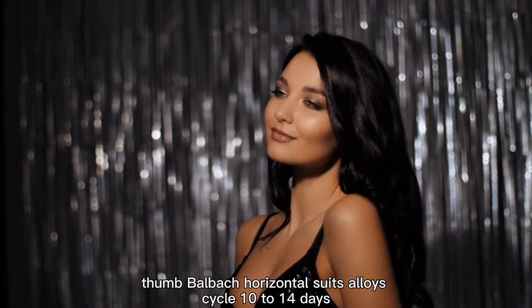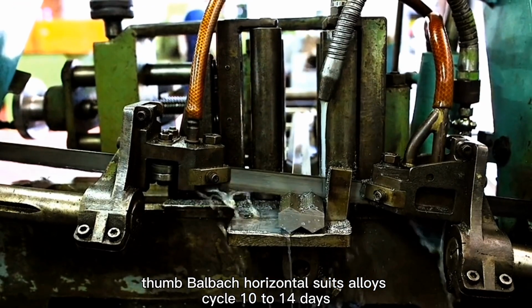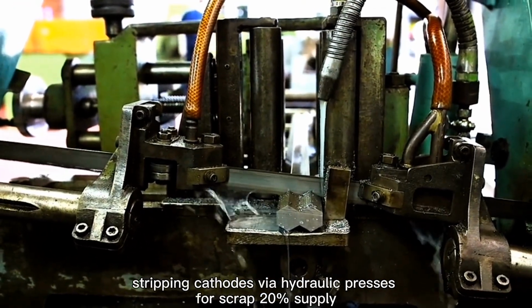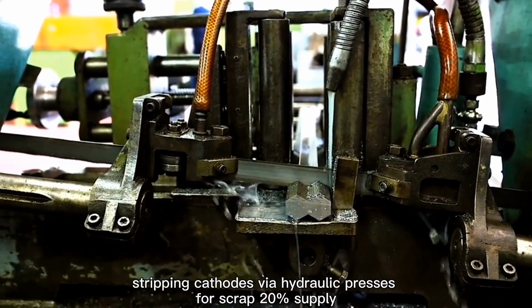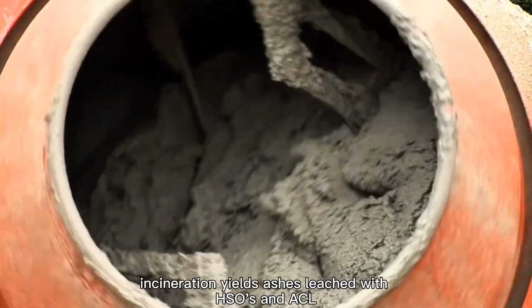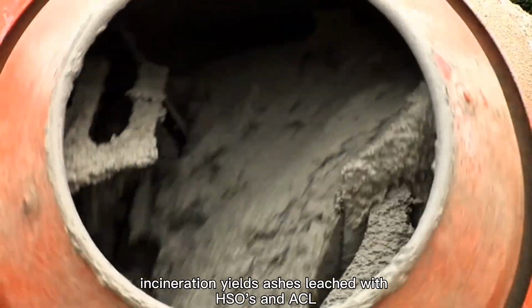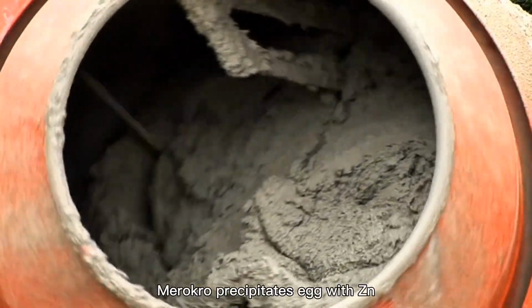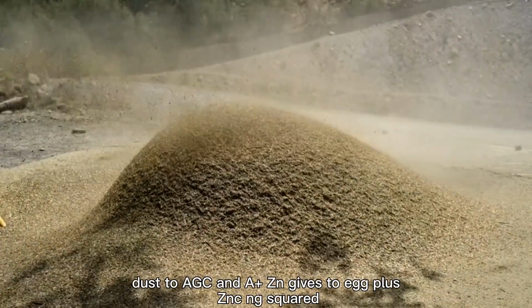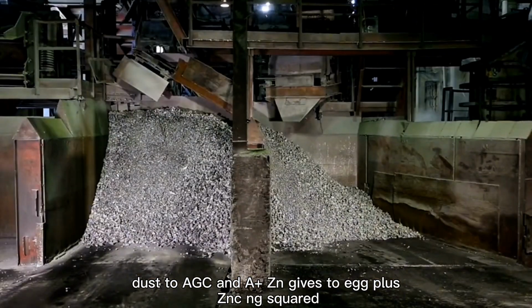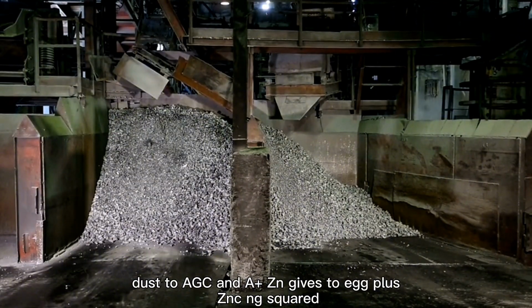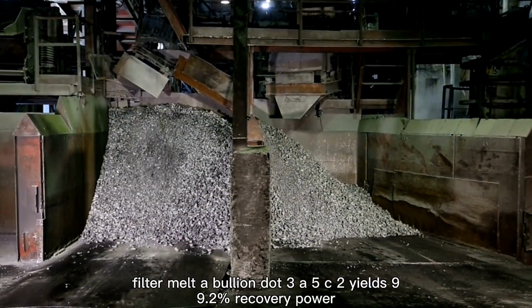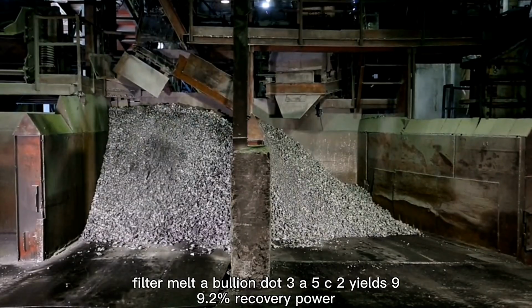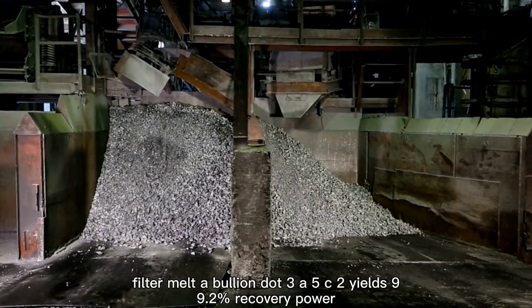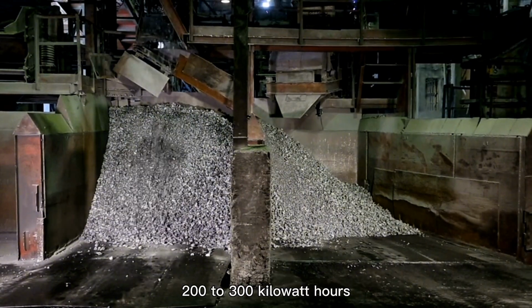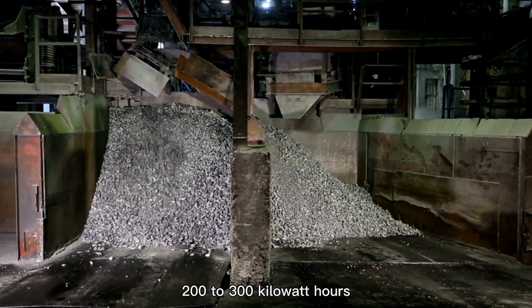Thum-Balbach horizontal cells suit alloys. Cycle: 10 to 14 days, stripping cathodes via hydraulic presses. For scrap, 20% of supply, incineration yields ashes leached with H2SO4 and NaCl; Merrill-Crowe precipitates Ag with Zn dust from Ag(CN)2-. Zn gives Ag plus Zn(CN)4 2-. Filter, melt to bullion. Yields 99.2% recovery. Power: 200 to 300 kilowatt-hours per tonne.